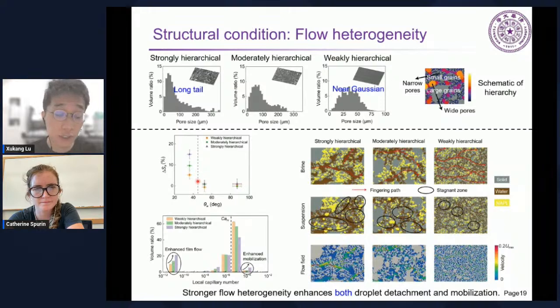So first, the corner flow criterion is always satisfied. So we always have this saturation increase only when this criterion is satisfied. And second, we see different performance in different structures. So basically, a stronger hierarchy, or we should say a stronger flow heterogeneity, will promote this saturation increase.